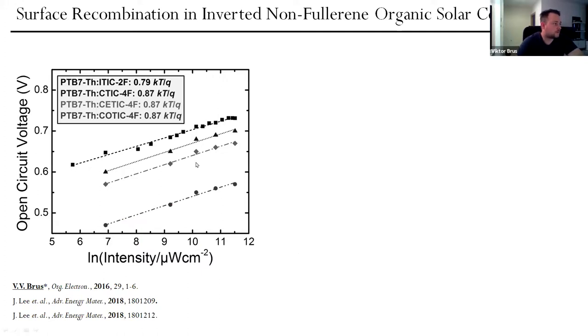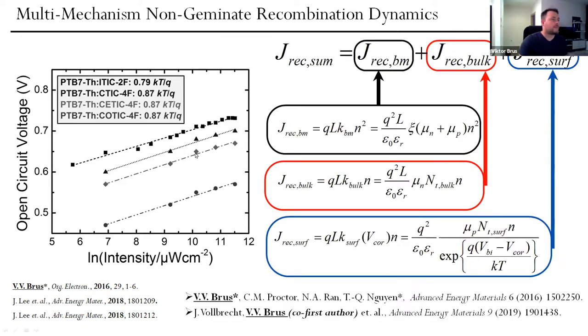recently we found a bunch of systems with slopes smaller than unity. And in the literature, there were previously reports of this VOC versus light intensity dependence with slopes less than unity, which doesn't fit into the model which we described previously when we have unity or more than unity. So here we have less than unity. So it took us some time to develop a full analytical model for multi-mechanism recombination dynamics in organic solar cells,